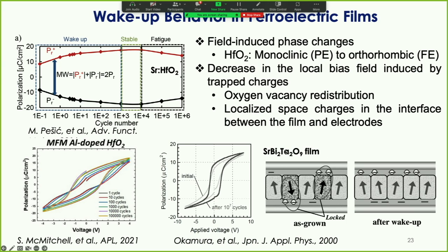In the perovskite and the perovskite layer structure materials, very often wake-up is associated with changing the defect chemistry in the material. So you can pin a polarization on any local electric or local elastic field. If you get the point defect concentration wrong initially, you can stabilize one polarization state over another. And we are pretty sure that's not how these materials wake up.